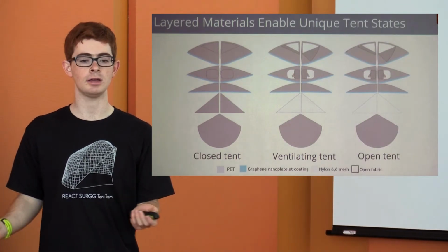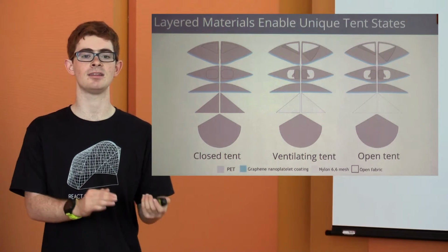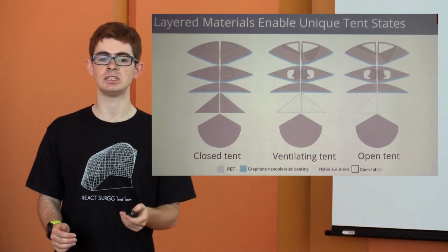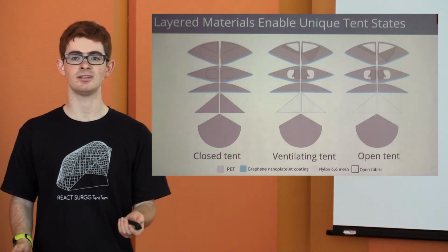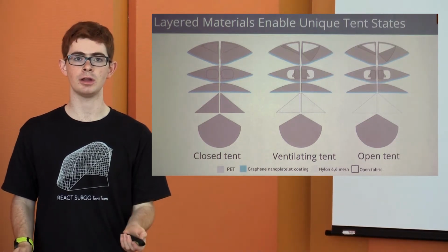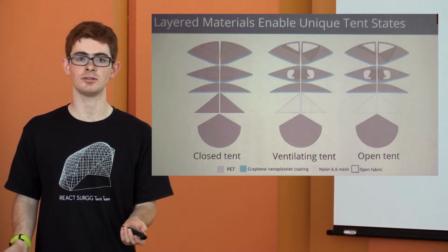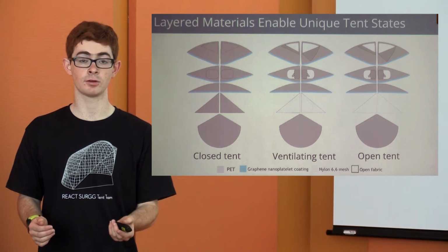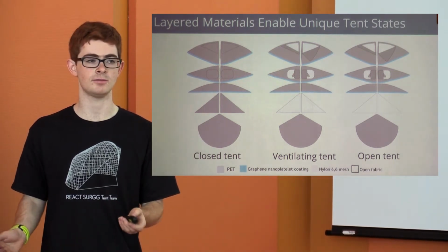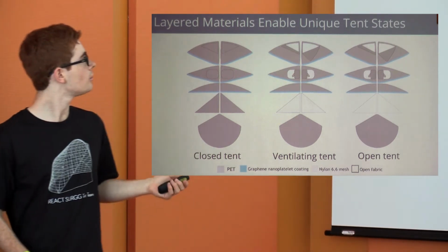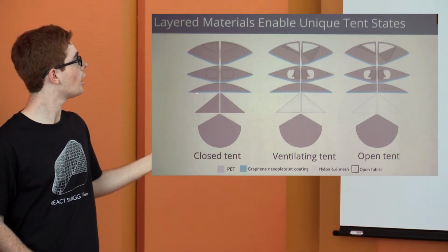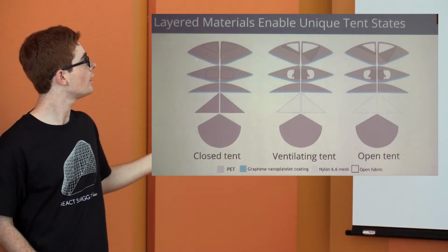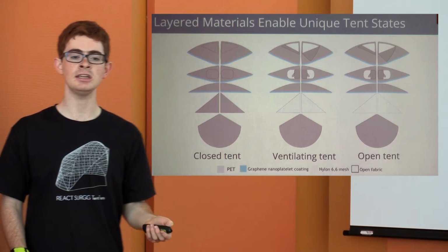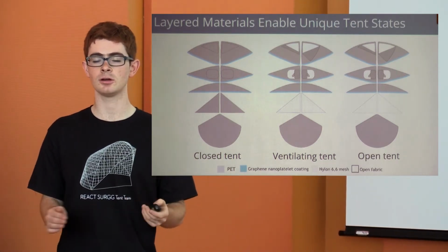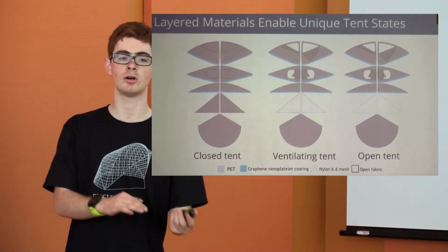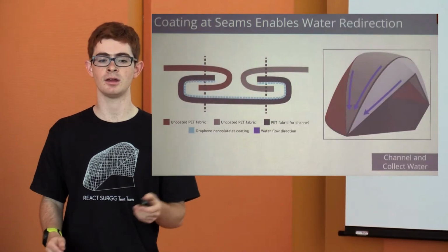We also finally incorporated the coating back into the tent design. So on these images, the light blue at the edges are the regions that are coated. And this coating, we should also mention, does not rely on fluorinated chemistry and is largely safe to interact with. So here, the coatings are along the edges there, and there on each of the 3 tents. And we can also modify whether the vents are open or closed depending on the environment.